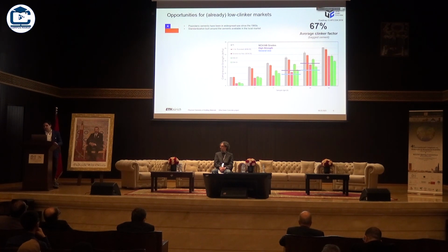And one of the strengths that we have, well, these are the two red bars that you see here in the plot. There is a high strength grade which has 80% clinker factor, and there is a general use which is this pink little one here which has 65% clinker factor, and then we are replacing that with calcined clay. And we wanted to compare these with LC335 and LC325, so 35% clinker and 25% clinker. The horizontal lines that you see here are the requirements of the standard for both grades of cement at 7 and 28 days.